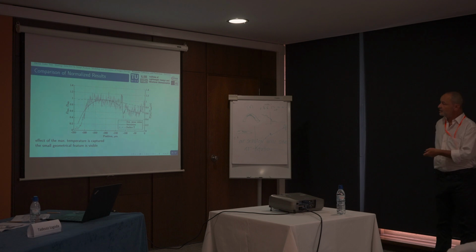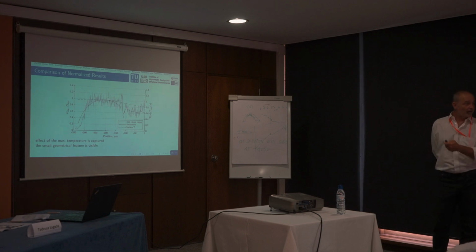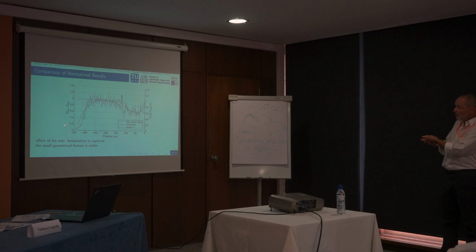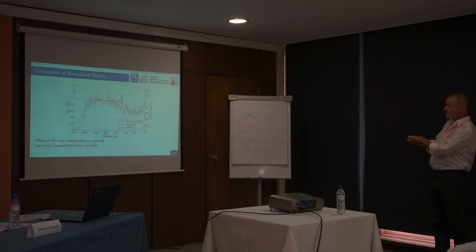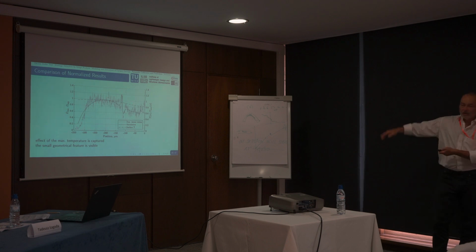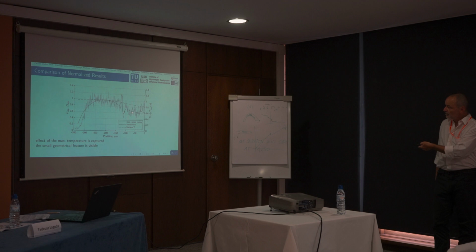Then we will compare this again, the mean over the 4 experiments. Again, still for design A, we have here our fitted Coffin-Manson law with the two parameters. You see it follows the trend quite nicely. So the maximum here, also this reduced damage or increased lifetime in the lower temperature area.